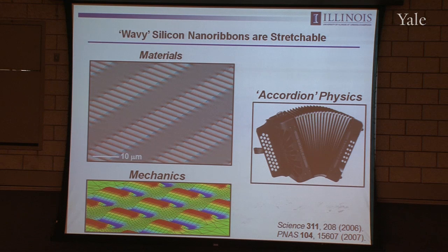I won't get into all of the details, but just give you a qualitative sense of it. If you take this very thin silicon, as I've argued, it's very flexible, very bendable, can be bent to a very tight radius of curvature. Now you take that silicon and you bond it against a rubber substrate that's slightly pre-stretched. After you bond it and you relax the pre-stretch, that induces compressive stresses in the bonded silicon. And the silicon, when subjected to those kinds of stresses on a soft elastomer substrate, will respond by undergoing a spontaneous nonlinear buckling instability that yields silicon in this wavy shape. These are strips of silicon about 180 nanometers thick, 10 microns wide, on an underlying silicone rubber substrate after that kind of process. And you can see this very wavy shape.